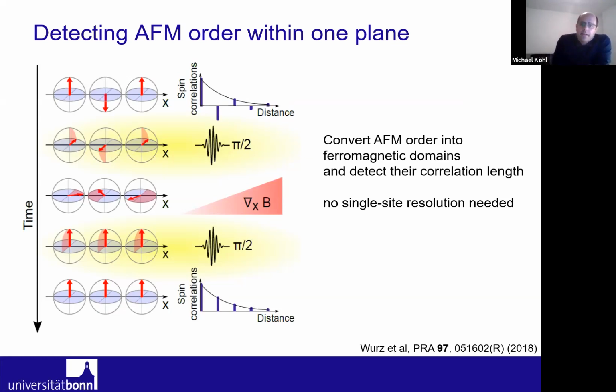And now we apply a magnetic field gradient, which leads to a precession of the spins. And the precession rate will depend on the location of the atoms. Actually, we can direct this magnetic field gradient into any direction along the lattice, so we can conduct this measurement into any k vector in the Brillouin zone. And if we have done the time evolution for just the correct time, then the spins which have been precessing, they have essentially all lined up into one direction.